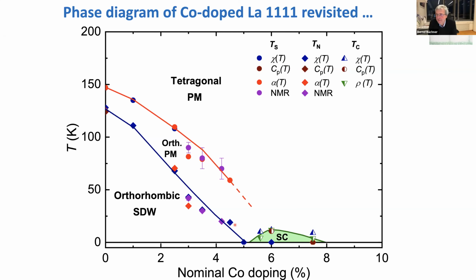Okay, probably. Already the fact that somehow this magnetism and the other transition change in a different way, one disappears previously, the other later on, might indicate that it's not the same instability which drives the system to the spin density wave or to the magnetic state, and the other one drives this nematic instability. But of course, a lot of theoreticians will disagree. They say, okay, that's fluctuations. Which I don't know. So that's what I can say.